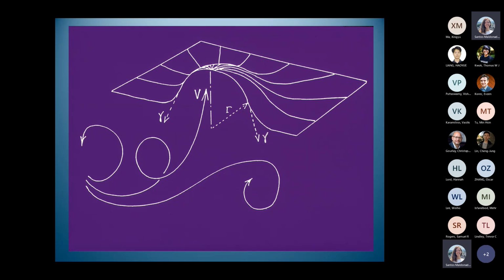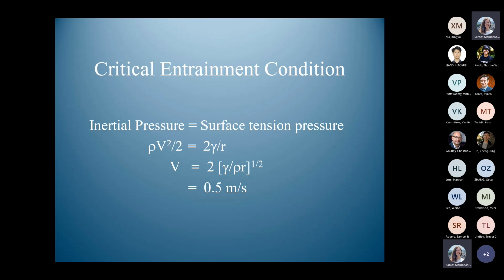And we can have a quick look at the simple physics of why it occurs and the critical conditions under which it occurs. Because if we just look at the surface, the surface is being tensioned by surface tension to keep it flat, but it's being perturbed by turbulence here in the liquid. So this is perturbing the surface with a certain velocity. And we can write down the critical condition at which these two forces, the inertial pressure in the liquid and the surface tension pressure, become equal. And we get a critical velocity of 0.5 meters a second.